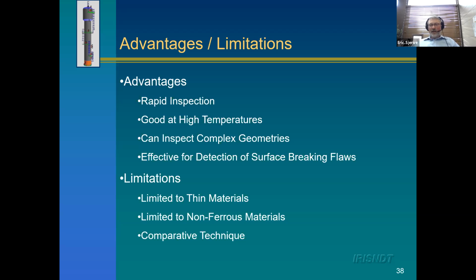It's really good at complex geometries because you can curve those coils into any configuration you want. And it's great at detecting surface breaking flaws. And the limitations are being limited to thin materials, and it also doesn't work on carbon steel well. So as soon as we say we have thin materials and it doesn't work on carbon steel, it really kills it for most of the Alberta applications.